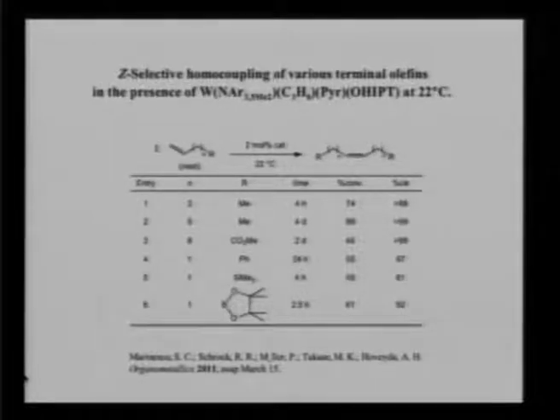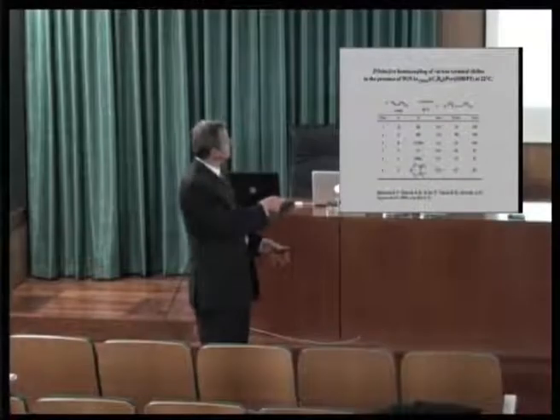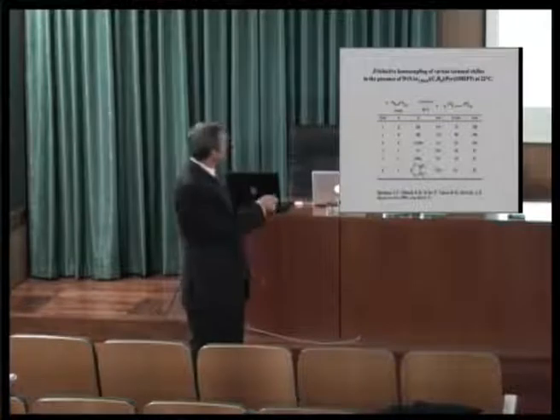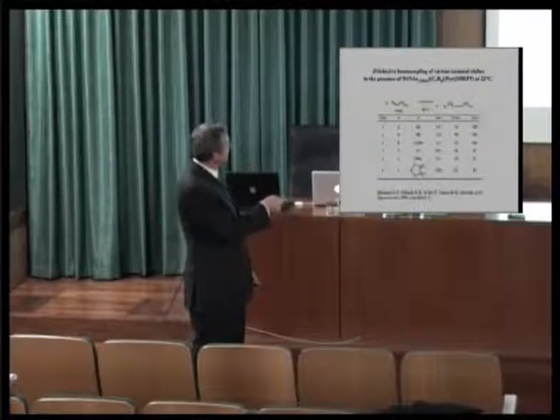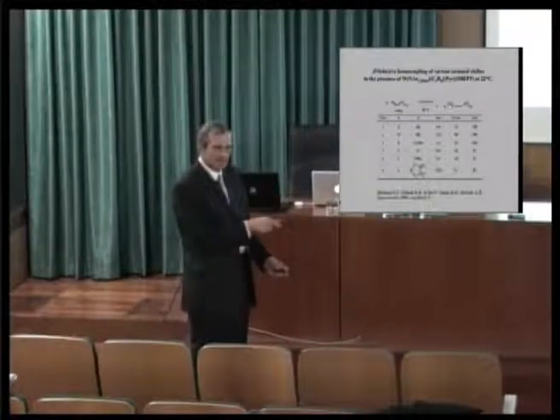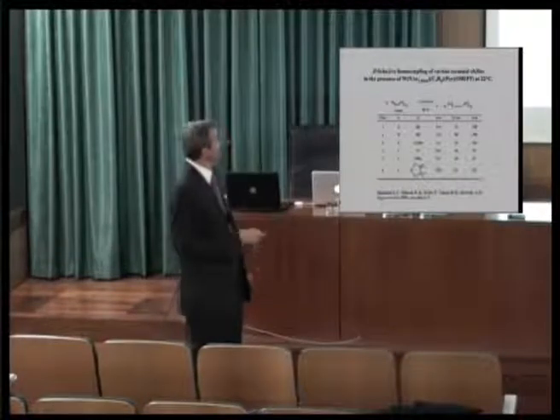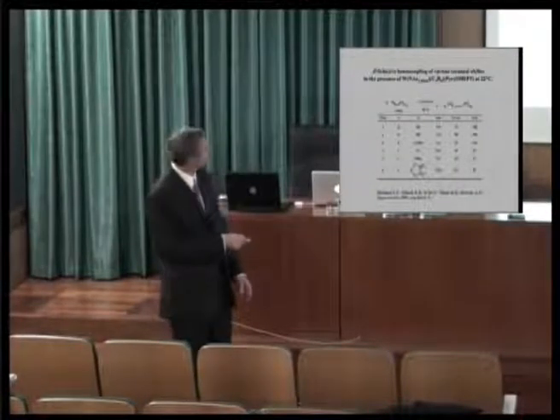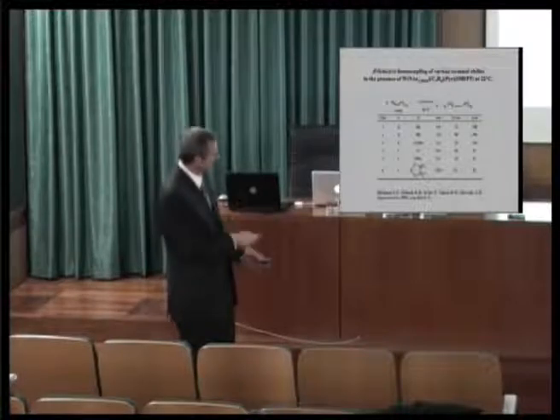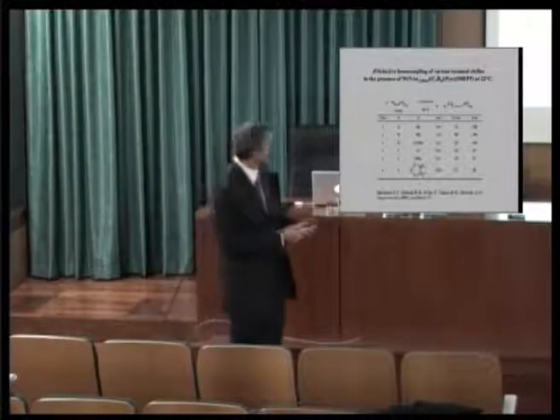2 mole% now, we think we can get the loading down to much lower than that. So you can actually now make olefins through homocoupling selectively Z. Now some of these don't work as well as others, and that means that you have to change the catalyst a little bit, and that will involve, of course, more research, and we hope that we can make this a general sort of reaction.